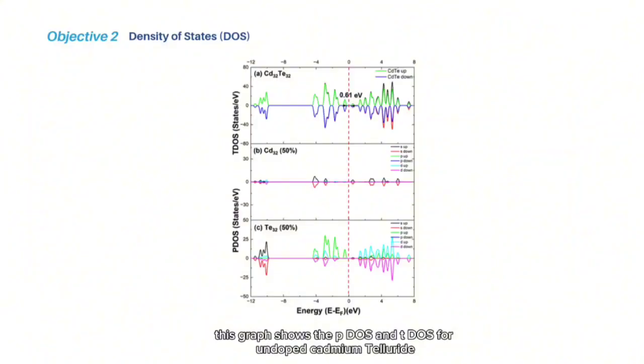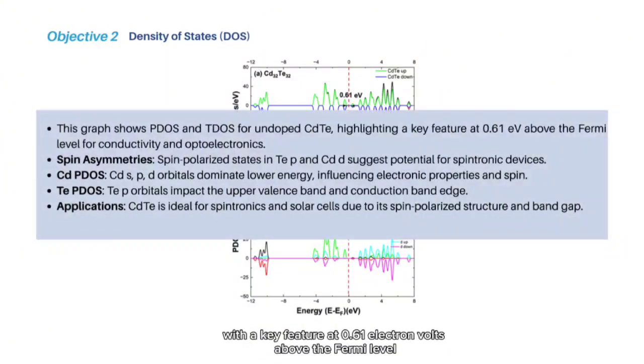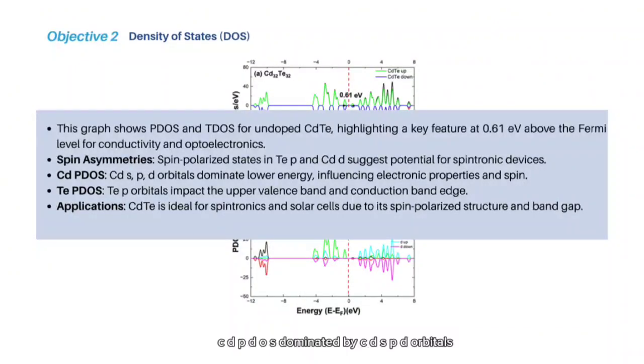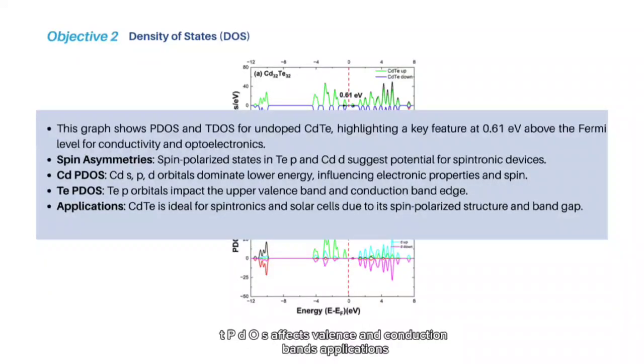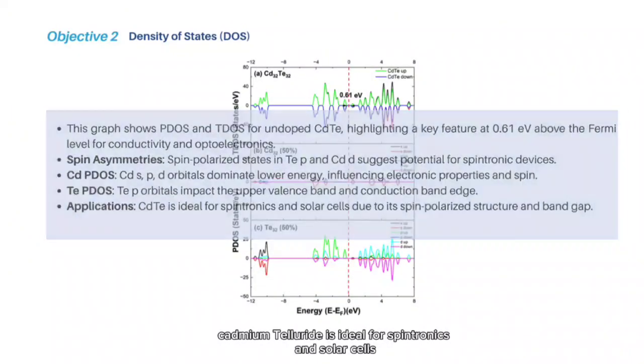This graph shows the PDOS and TDOS for undoped cadmium telluride, with a key feature at 0.61 electron volts above the Fermi level, essential for conductivity and optoelectronics. Spin asymmetries. Te p and Cd d orbitals suggest potential for spintronics. Cd PDOS, dominated by Cd s, p, d orbitals. Te PDOS, affects valence and conduction bands. Applications. Cadmium telluride is ideal for spintronics and solar cells.